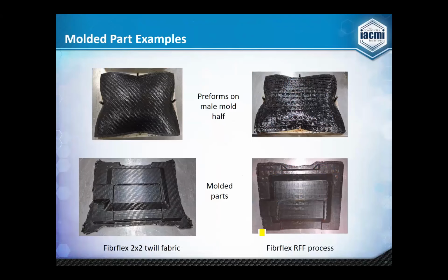What was beautiful about this part is you can see that there are very steep walls in this tool, and that was because we were competing against a machined aluminum, which was virtually 90 degrees. We did make these roughly, I think, around 2 degrees draft. But it also has many other very interesting contours. At the top, on the left side is a 2x2 twill fabric preform. There are 3 plies there. That 3 plies makes a 45 thousandths wall. On the right, we have the RFF preform.